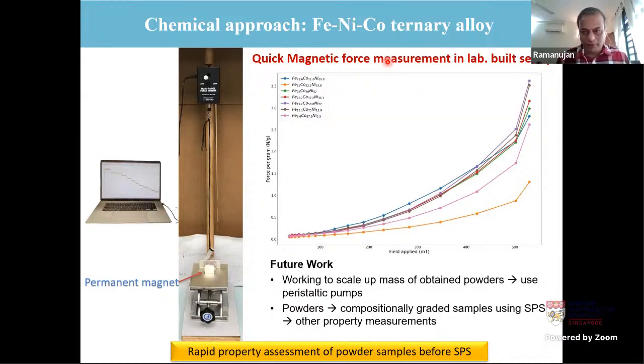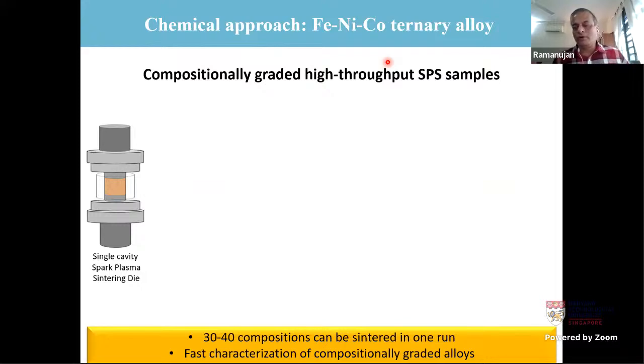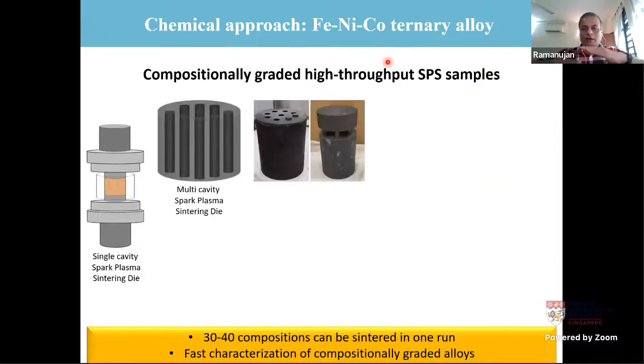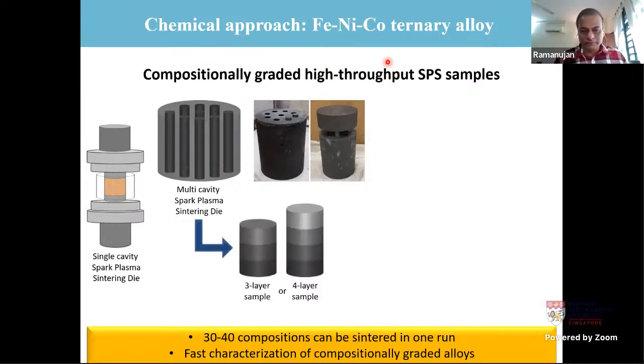And of course, if you look at it from a physics standpoint, the force that the permanent magnet exerts on these powders is related to the permeability and other properties of the powders. Once we have produced these powders using this chemical approach, we then subject them to spark plasma sintering. So now we have a graded sample produced by this chemical method, and we can make bulk samples. We can make 3-layer samples, 4-layer samples, or in principle, any number of layers. And we sinter them so that we get a bulk material which is easy to characterize and evaluate the properties of.